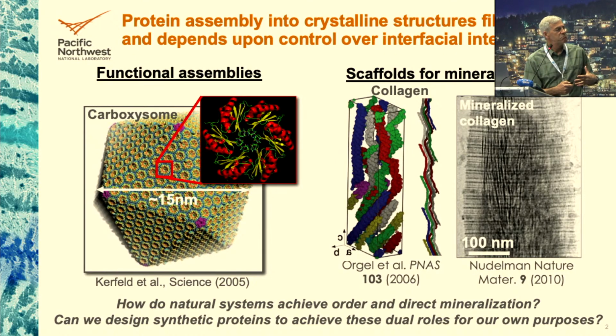So it's this sort of hierarchical structure that ends up being functional, but it's the self-assembly process that needs to be controlled in order to produce it. Now, the reason it's functional is because the assembly creates these pores where you have these peptide loops that stick into this region, and that controls what goes in and can come out of this vesicle. In this case, it's bicarbonate ions, and they get turned into fixed carbon by enzymes inside like Rubisco.